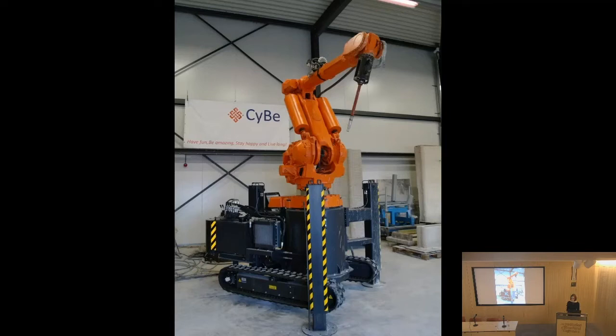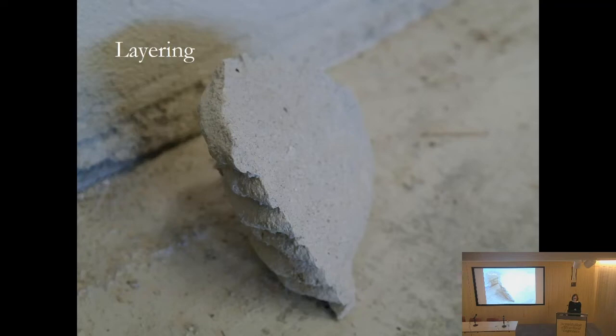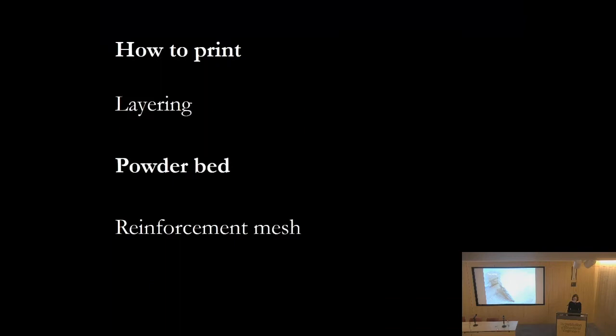For all layering methods, you have to mount the nozzle on something. With contour crafting, a gantry is used, but this limits the area you can reach — your gantry has to be bigger than the element, making it uneconomical beyond a one-story house. With a robot arm, you can move the nozzle around and adapt to the site. A cross-section of a printed element shows that there's really not much difference between the concrete in one direction versus the layered direction.